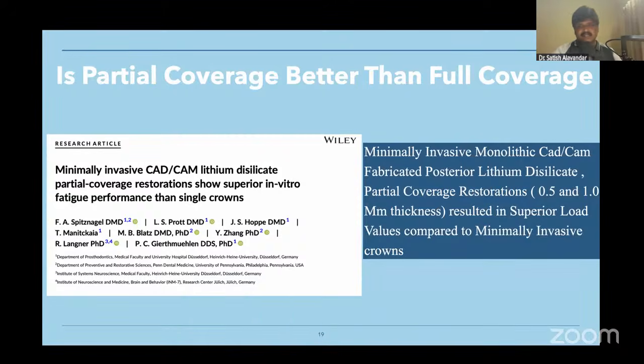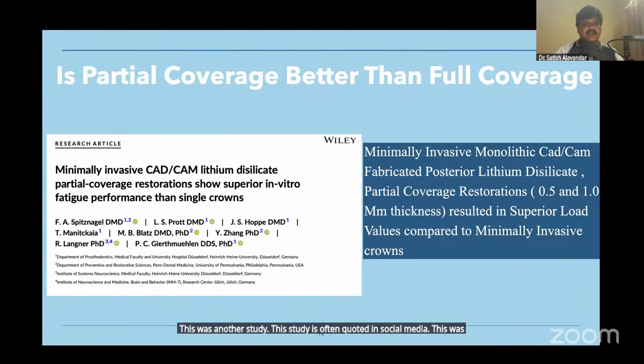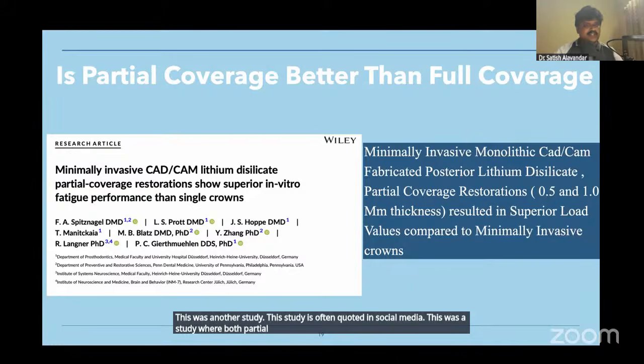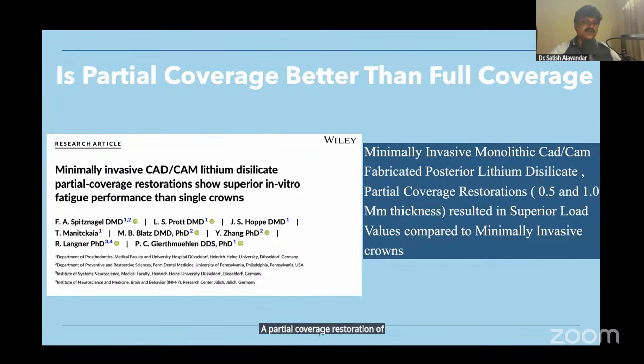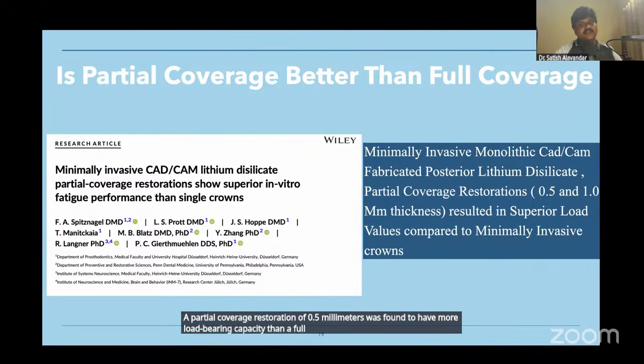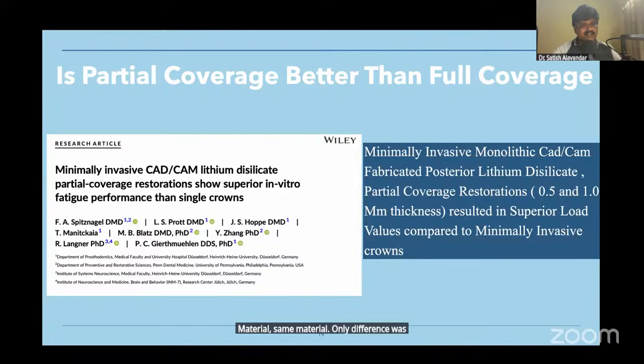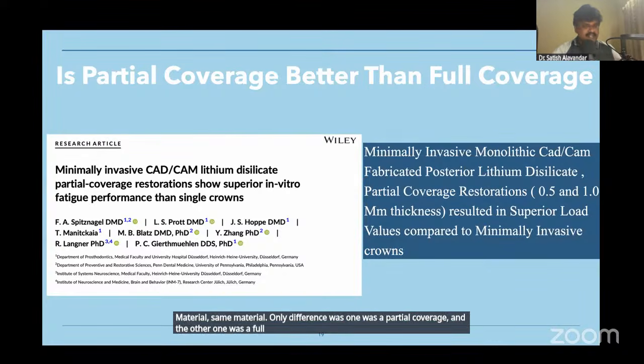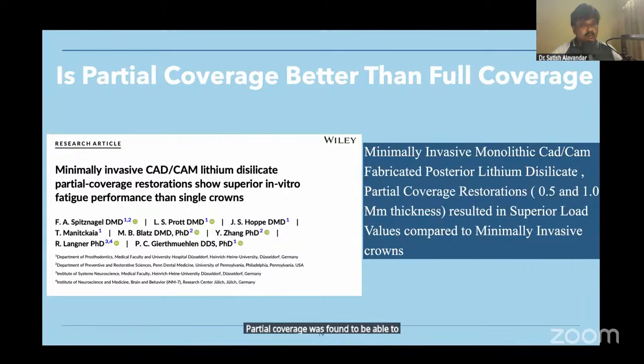This was another study, which is often quoted in social media. This was a study where both partial coverage restorations and crowns were made of different thicknesses. The take-home message from this particular study is that a partial coverage restoration of 0.5 millimeters was found to have more load bearing capacity than a full crown of the same 0.5 millimeters thickness. Same material. The only difference was one was a partial coverage and the other one was a full crown. Partial coverage was found to be able to withstand more load compared to full coverage.